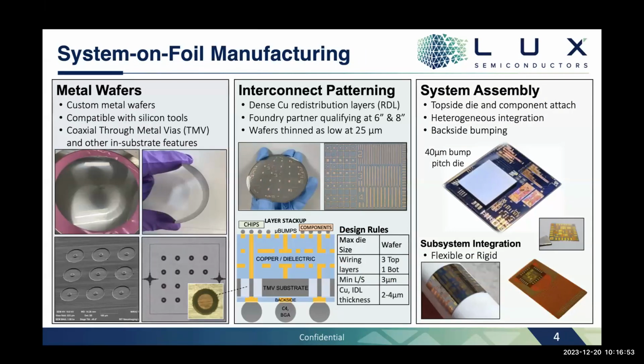Okay, so getting into a little bit more of the specifics, really this all starts by taking a sheet of metal and making it into a wafer, and specifically a wafer that has similar mechanical specs as that of a silicon wafer, so that it can be handled using automated fab equipment. It does not go into the front end of the line, but it does go into the back end of the line and receives the same type of interconnect processes that our chips would today, the higher level interconnects of our chips today, and also silicon interposers that are not using a spin-on RDL process. So we make these bare metal wafers.